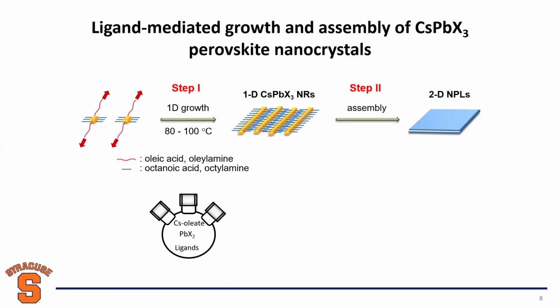One is the long ligands, like oleic acid or oleylamine, which have an 18-carbon hydrocarbon tail. These are organic molecules. Another set of ligands is the short ligands, octanoic acid, which only has an 8-carbon hydrocarbon tail. So our idea here is that the short ligands bind on the side walls with higher packing density. But the long ligands, being bulky, bind on the tips with larger free volume between them because of a steric effect, where we need more space. So then you have different surface energies, with the side walls being protected and lower energy on the tips. More free volume can keep adding reactant on the tips, which can boost one-dimensional nanorods. Okay, that's our idea.